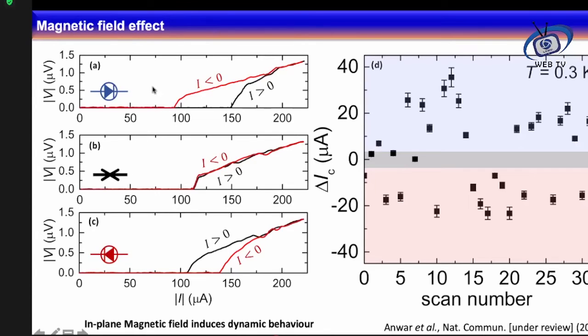Let me explain it in a simple way. For example, we applied a magnetic field, then we switched off the magnetic field. There is no magnetic field. The effect of the magnetic field is still there because it was in the superconducting state. And then what was happening is that here in this first IV, you can see that the critical current for positive and negative is different, because this is in absolute values of the voltage and current. So then I can call it a forward biased diode.